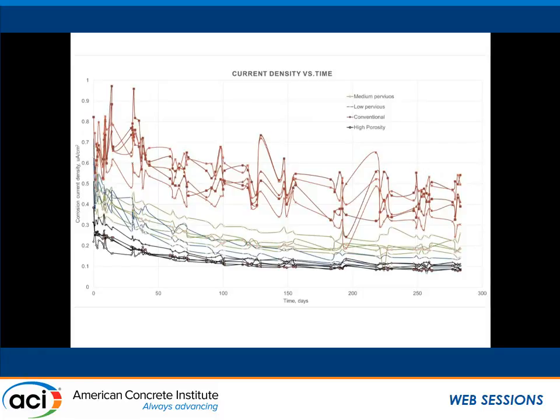We've got humidity sensors in there. We've got a much lower humidity in the pervious layer than in the conventional concrete layer. So something's happening. What we're going to do is once we hit a year, we're going to take half of the samples and induce a voltage or current through them to try to accelerate and see if we can differentiate between them.